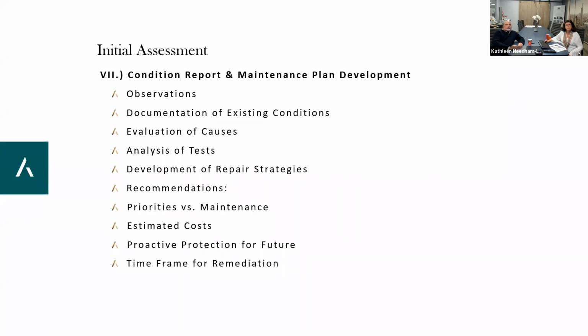In this situation, we need to determine the compressive strength. We send it out to a laboratory. As you see, this particular sample has an average of almost 4,100 PSI, so the engineer will determine if that's appropriate. We're looking to see the chloride content of the concrete when doing the evaluations, and so the core is sent to a testing laboratory to measure the chloride, the salt content.